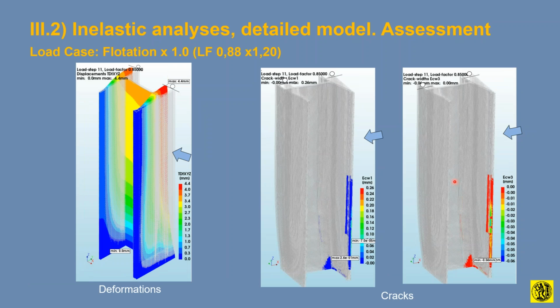Now the flotation. Pretty much the case is the same as in the shell analysis. 4 millimeters is the maximum in-plane bulging of this chamber. But you can see that already this behaves as a cantilever, pretty much fairly down. So actually, the shear deformations are pretty high down here. This more or less behaves as a fairly constant cantilever.